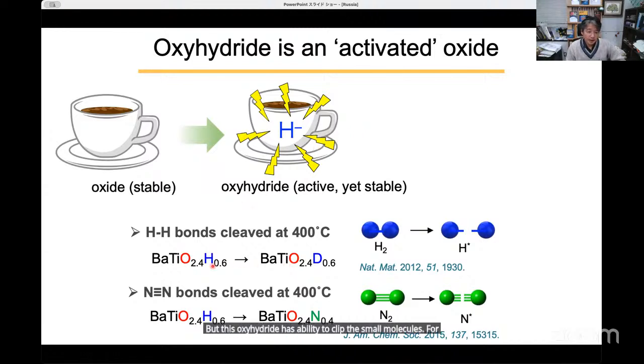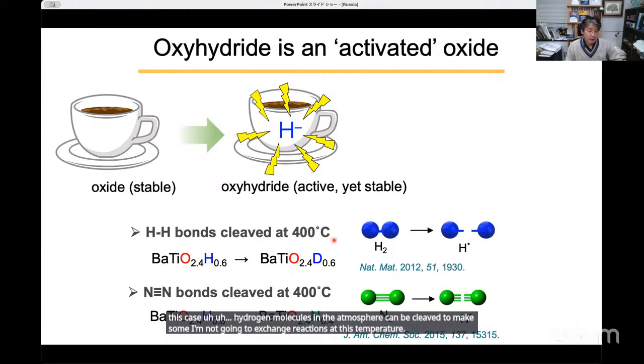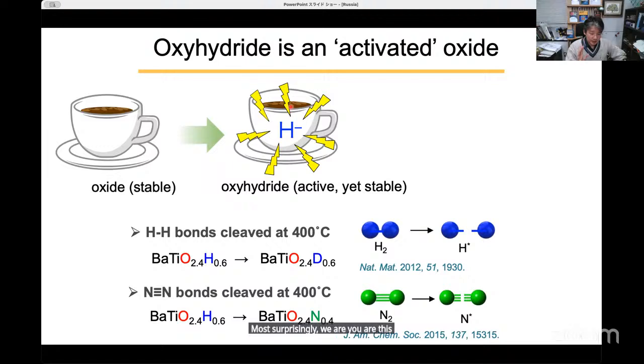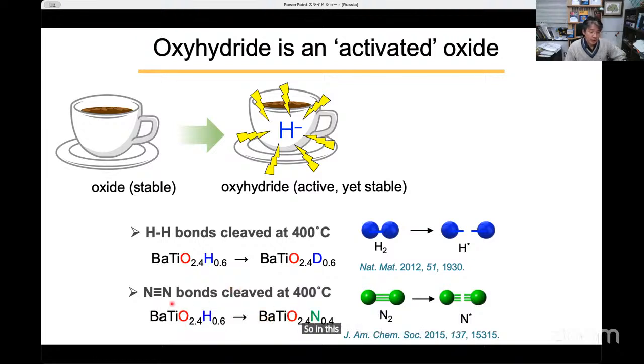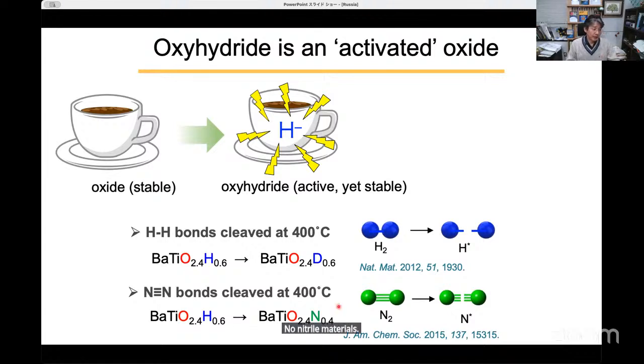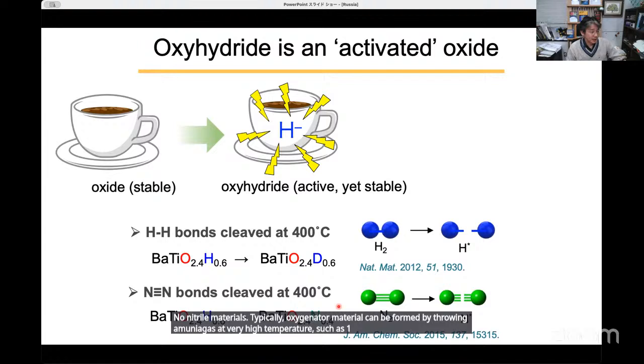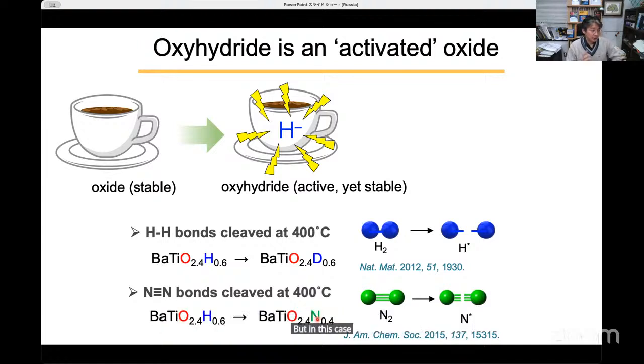For example, in this case, hydrogen molecules in the atmosphere can be cleaved to make anion exchange reactions at this temperature. More surprisingly, this material can cleave the triple bond of nitrogen. In these reaction conditions, the nitrogen triple bond can actually be cleaved, and this oxyhydride is changed into an oxynitride material. Typically, oxynitride material is formed by flowing ammonia gas at very high temperature, such as 1000 degrees C. But ammonia is very toxic. In this case, you don't need to use ammonia gas; very inert nitrogen gas can be cleaved to form oxynitride materials.